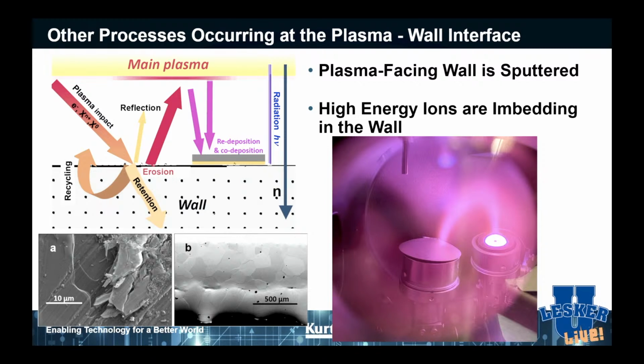These are relatively closed cycle systems, so you do see some redeposition, but that tungsten surface is being continuously eroded. You're seeing this kind of damage here. Look at the temperature. This got so hot, obviously, that it melted and then recrystallized. We're talking about extreme temperatures, and there's a lot of work going on just to try to keep the plasma away from the walls of the reactor.